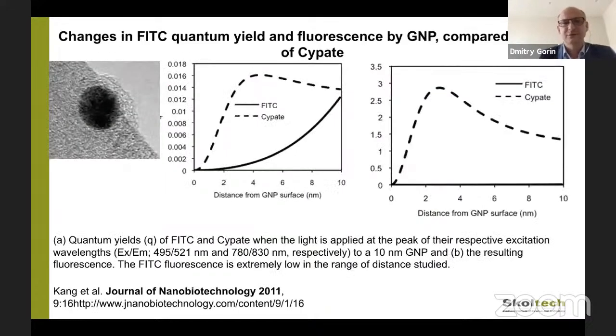And then we go to the physical phenomena that we are going to use for preparation of a bimodal photoacoustic and fluorescence contrast agent. And we use for this an idea published in this work. Here you can see gold nanoparticles, and if you coat the gold nanoparticles with polymer layers using the layer-by-layer approach, you can change the distance between the dye and the surface of the gold nanoparticles. And you can see that there is an optimal distance where we have enhancement of fluorescence. And if we adsorb our fluorescence dye exactly on the surface of gold nanoparticles, we obtain quenching of fluorescence.